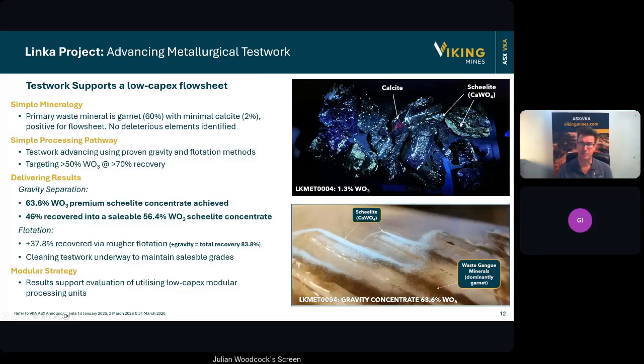Now, this is the sample that we then subsequently crushed and ground, and then we put initially through a gravity separation method, which is the first step. The second step is flotation. Through the metallurgical test work, we're targeting a grade of a concentrate greater than 50%. This is significant because 50% is really above the limit that we need to achieve in order to be able to have a marketable product, and we're targeting more than 70% recovery.